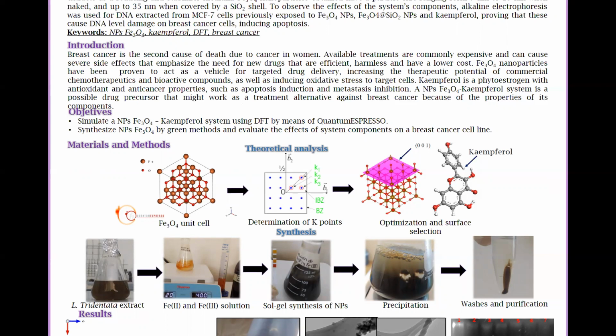The cubic structure of the 227 space group consisted of 56 atoms with octahedral sites for iron 2 and half of the iron 3, while the other half of the iron 3 was in tetrahedral sites. We worked with a ferromagnetic behavior and a 3x3x3 mesh. The relaxed structure was then taken into a surface slab on the 001 plane, which has the most stability. Periodicity was carried with a 20 Angstrom vacuum. In the same cell, we added KAEMPFEROL to further relax, only this time we used gamma for K points under